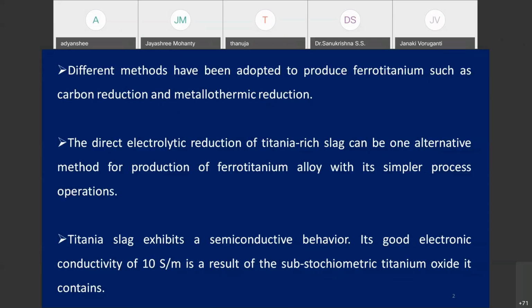If FeO or Fe2O3 plus TiO2 plus ZnO, zinc oxide, zirconium oxide. If you take a mixture of metal oxides, they can also be reduced to their respective metals in that particular substance. So they will give you a mixture of metals. Since ilmenite is a mixture of metal oxides, and your slag is a mixture of metal oxides, they can be a source of your starting material. So you first choose the titanium slag for this process as the starting material.